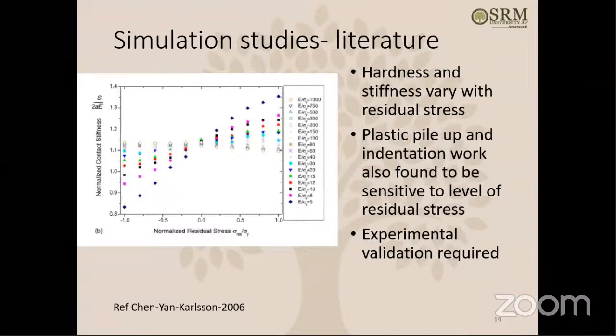The conclusion from this literature analysis is that hardness and stiffness vary with the residual stresses. Plastic pileup and indentation work were also found to be sensitive to the level of residual stresses, and experimental validation is required. So this is basically the motivation. In all this analysis work, there was no experimental validation, so we went ahead and did some experimentation on this.